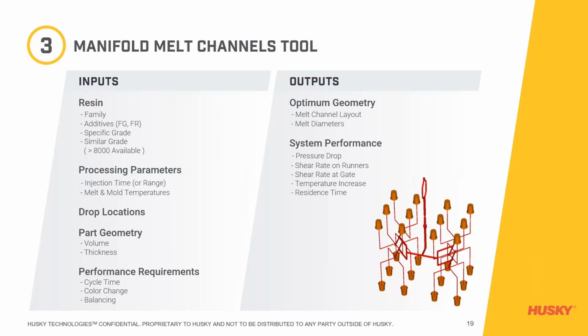As the resin is flowing through the hot runner, it's picking up heat as a result of that shear rate. We want to know what that temperature increase is. Specifically, we want to make sure we keep it under the limits set forth by the resin supplier, so we're not degrading the resin. And then finally, residence time. Residence time is simply how many shots you have in the melt channels of the hot runner system.